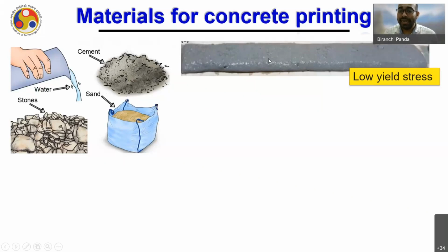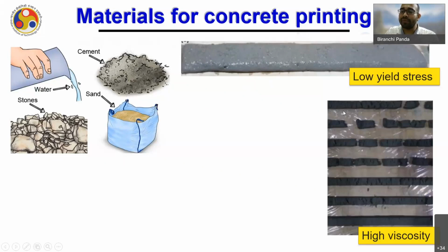But considering the need of my pumping process, I have to create a very flowable mix. But if I simply deposit this flowable mix, it is going to flow away on the print bed. So neither do I need this kind of material, nor a very stiff material. Because if I have a stiff material, I have to apply very high pressure for pumping. And once I deposit, the layers will not be continuous, rather they will be discontinuous in nature. So this is the problem with high viscosity material.